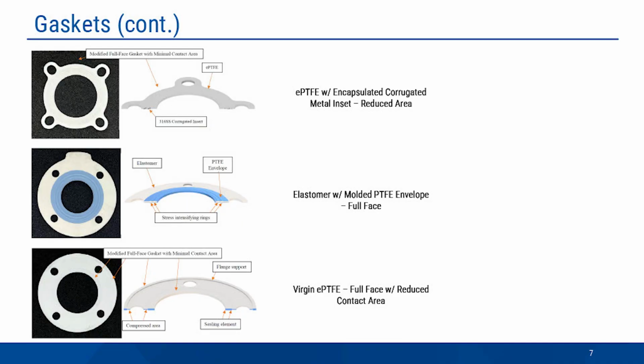The next is an expanded PTFE gasket in a reduced area design. However, on the ID of the gasket, it has a fully encapsulated corrugated metal insert. What that does is twofold. One, when you compress the gasket, most of your stress is going to be applied to the peaks of that corrugation. So you're thereby increasing the effective gasket stress because you're concentrating it on a smaller area. What it also does is that metal insert acts as a spring. So any sort of external loads, whether it be thermal cycling or vibration, where you would typically lose load in another even virgin expanded PTFE gasket, that spring live loads the gasket, so you're going to maintain that gasket stress throughout your external loads.